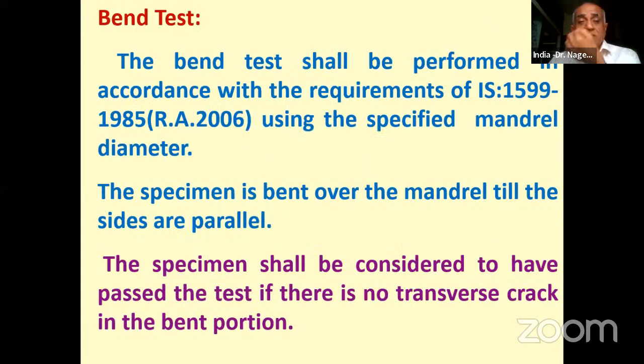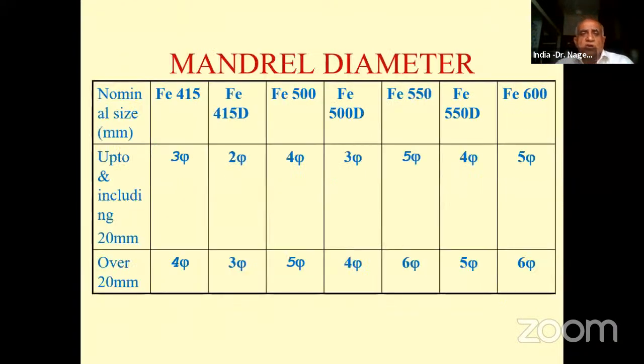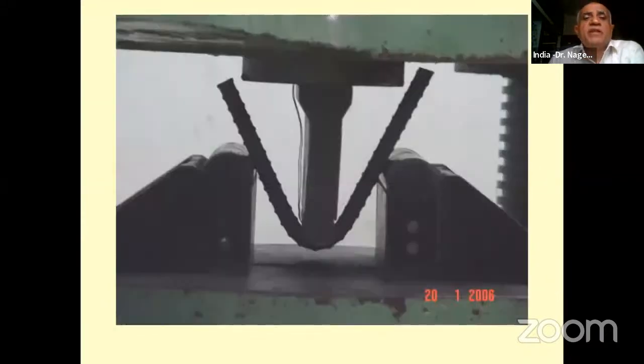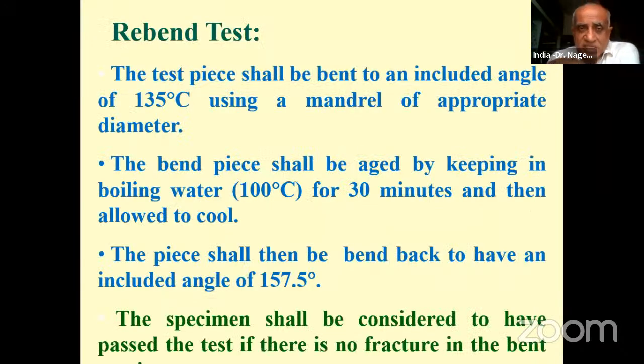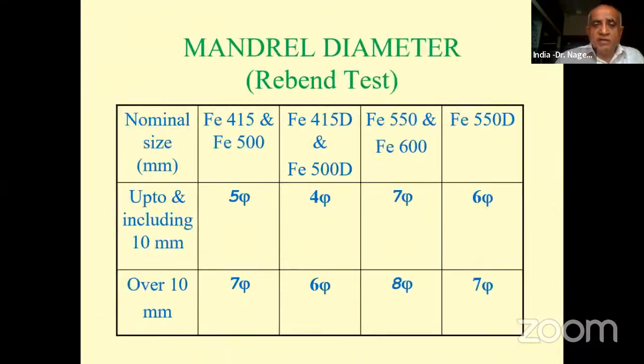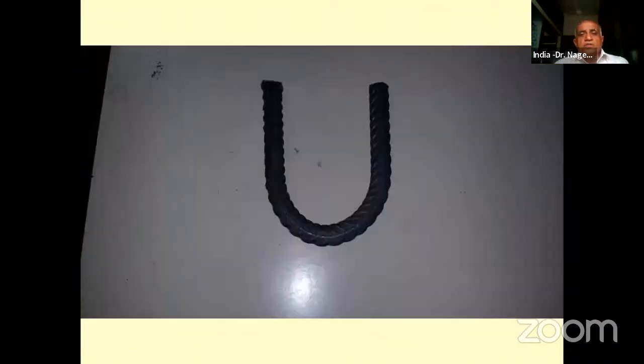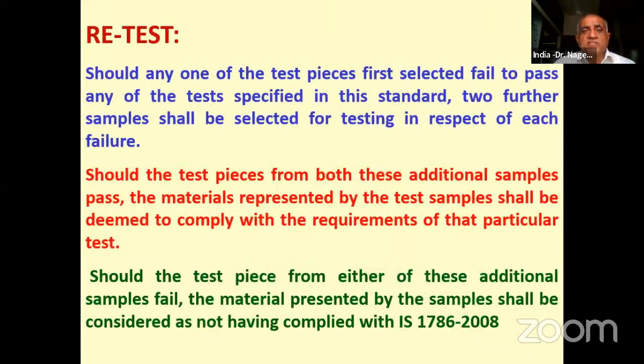So bend and rebend test. Bend test is a very simple test. You have to bend it using various mandrel sizes. You have to bend it into 180 degrees like this. And then there is a test called rebend test. Rebend test is done on another sample, not on the same sample. So angle is 135 degrees. And this is what you can see here, the various mandrel sizes you have to use. So this is for a bend test, and this for a rebend test.